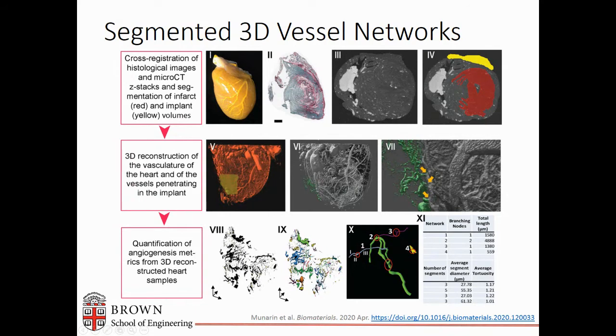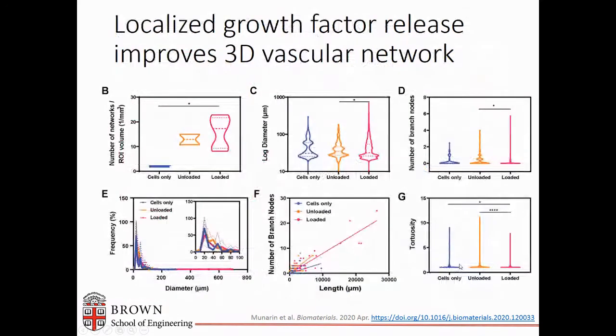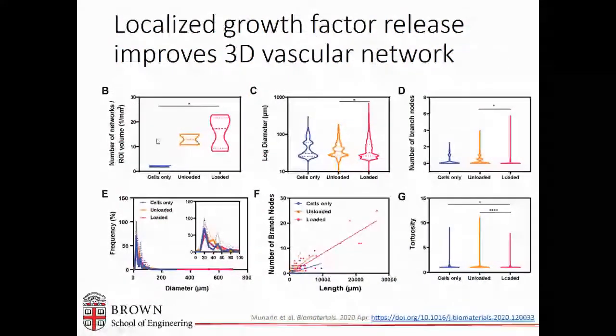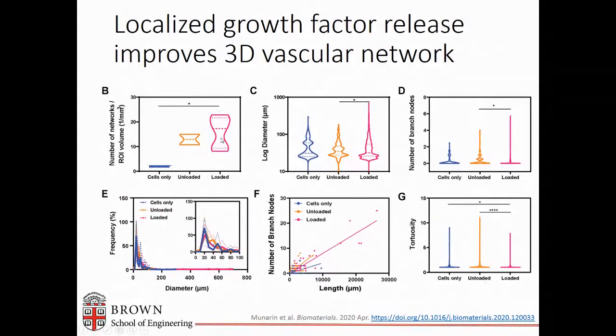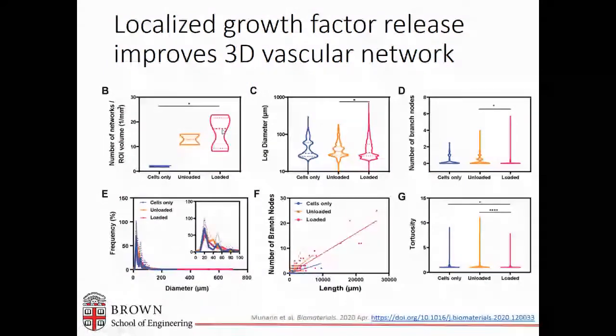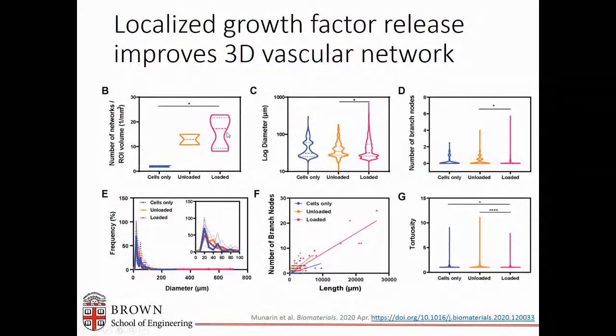And then we quantified the vascular networks that were in the engineered tissue. What we found was that the number of networks per the volume of the tissue was increased in the loaded condition compared to the cells only condition, shown here in this violin plot. And then also the diameter was increased in the loaded versus the unloaded condition. The number of branch nodes also increased when we had the growth factors loaded into the microspheres.